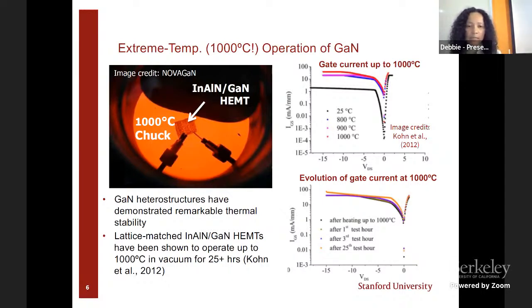And I was really captivated by this work, right? The ability to transduce, create a transistor at 1,000 degrees Celsius. So these are the current voltage response. So the gate current up to 1,000 degrees Celsius. So the black curve is room temperature, all the way up to 1,000 degrees Celsius. And then if you hold that at 1,000 degrees Celsius, the evolution of the gate current. So this is after various heating cycles. And so we're seeing that these curves overlap, which is nice. That's what we like. But unfortunately, this is in vacuum.